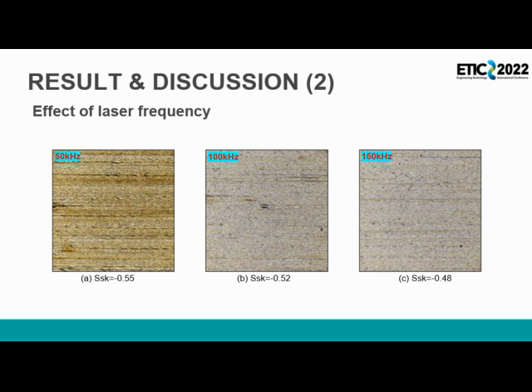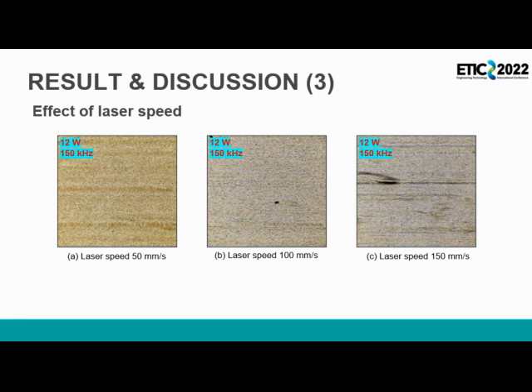The figure above depicts that as the laser frequency increases with both laser speed and laser power kept constant, the surface profile is better and smoother. At laser frequency of 50 kHz, the skewness value is negative 0.55. Meanwhile, the skewness for laser frequency at 100 and 150 kHz is smaller. The surface profile is smoother at laser speed of 100 mm per second, but gets a little worse at laser speed of 150 mm per second.